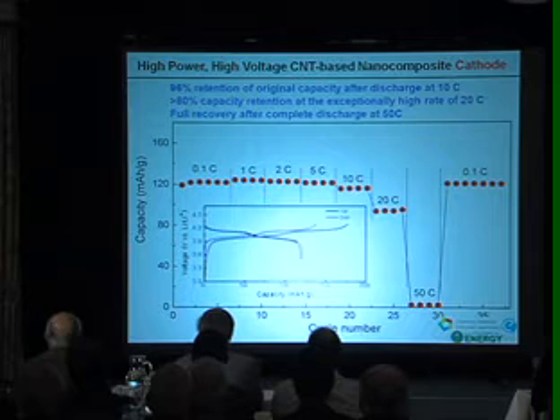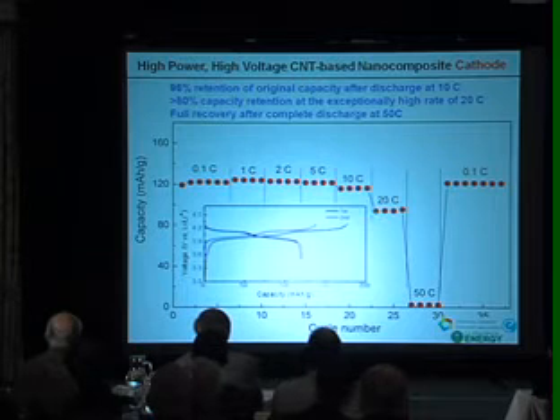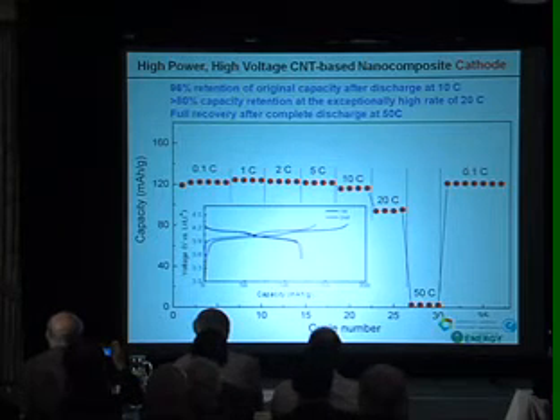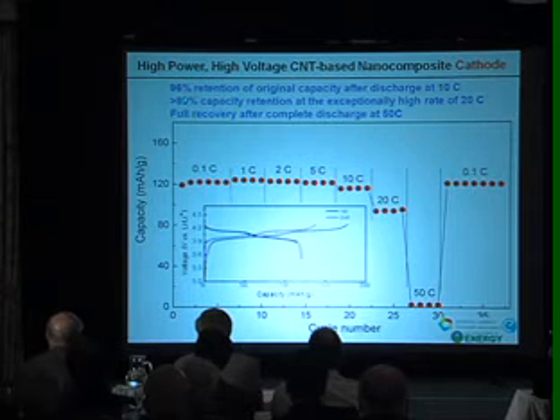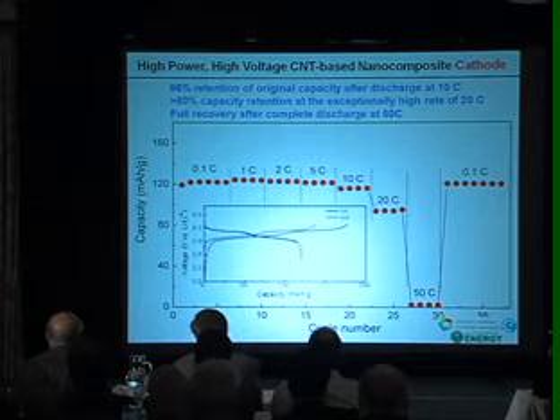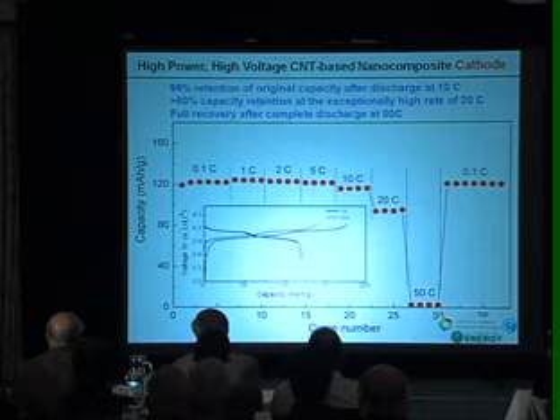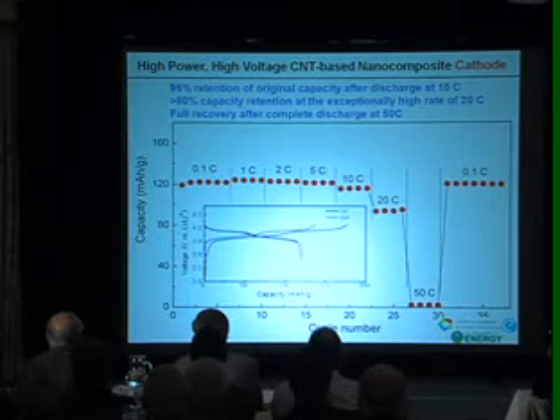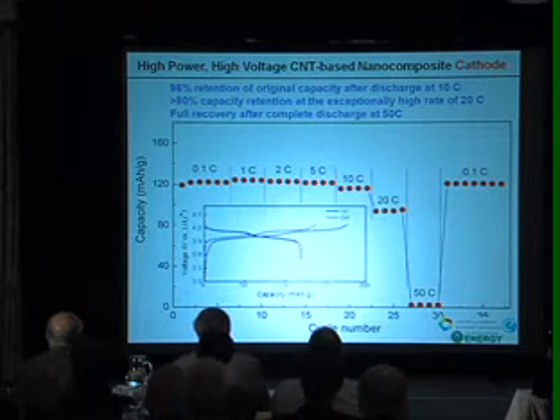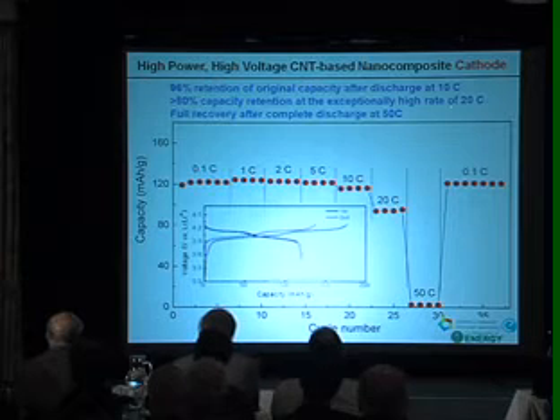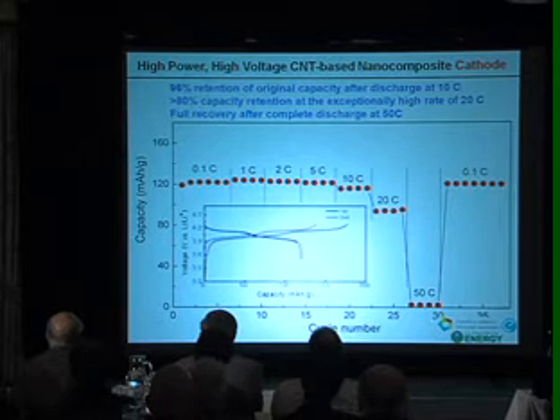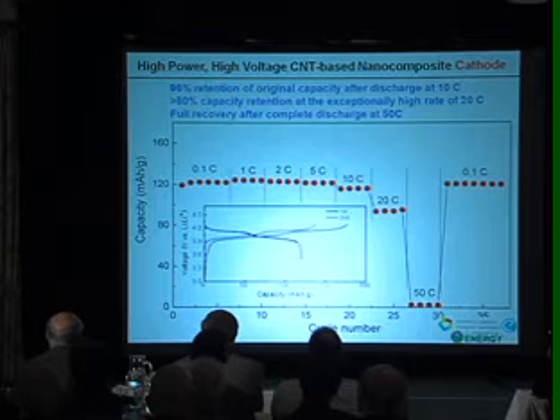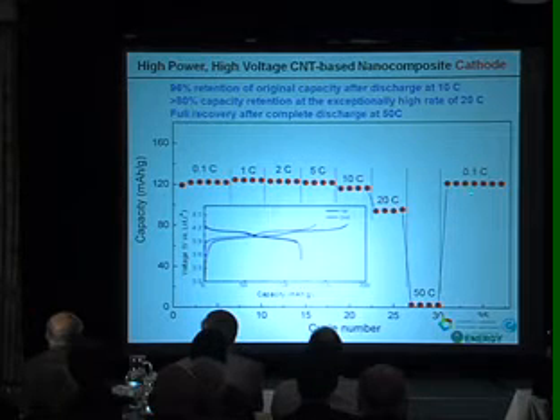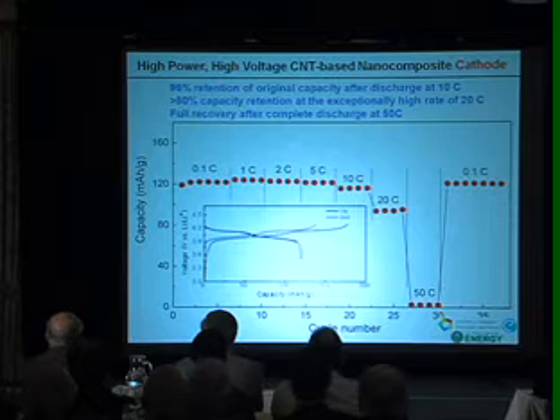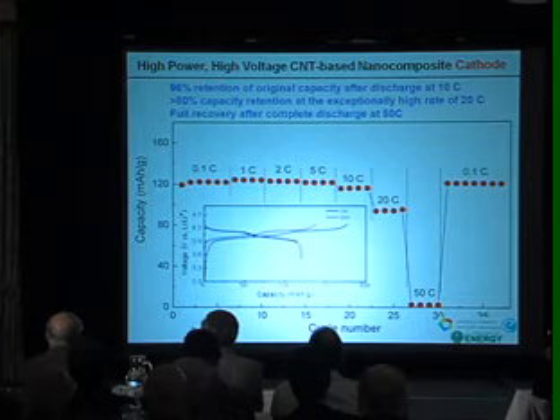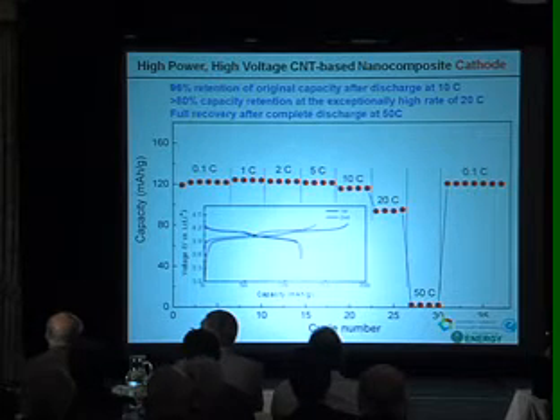Here's the electrochemical capacity of that high-power cathode, and it too is exceptional. It shows 98% retention of the original capacity after discharge at 10C. Greater than 80% capacity retained after the exceptionally high rate of discharge at 20C. It's fully exhausted at 50C, but bounces right back. Complete recovery. And this curve here shows that this is a very high voltage cathode at about 4 volts.